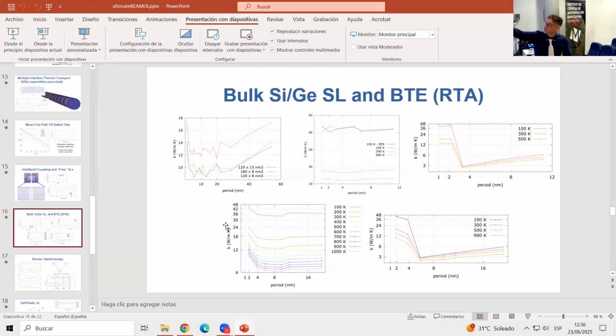And that's why we have to simulate very long periods in order to restore the linear increase in the thermal conductivity as a function of the reciprocal interface density. For the transport equation, for the Boltzmann transport equation,